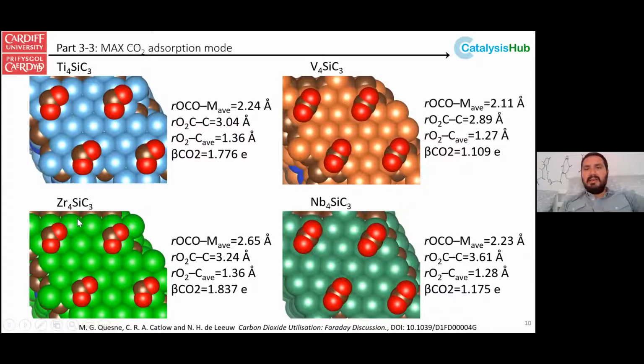So this is a picture of the most favored adsorption sites on each silicon carbide surface. What you see is that the adsorption morphology that's the most favorable depends quite strongly on the geometry of the surface. So these two adsorptions, where the CO2 is sitting perpendicular, the carbon in the hollow site and the two oxygens bound to adjacent carbons, or the one where it's more perpendicular. Both of these have been seen also in the metal terminated carbon surfaces, and they're very close in energy. But again, it depends very much on the local geometry of the surface.